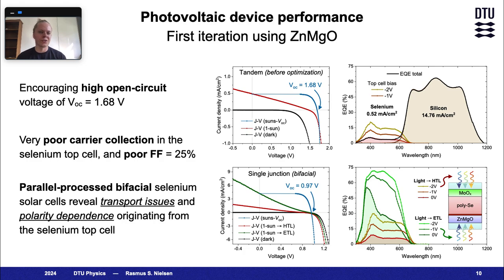Fortunately, all of the issues that we encountered on the tandem were actually reproduced on the single junctions, revealing that as we swap out gold and FTO with ITO, there's a huge problem with charge transport, and we observe a very strong polarity dependence as well.